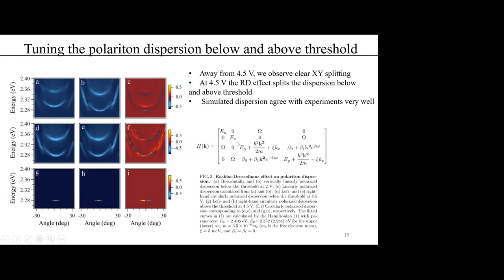In theory, we use this model, which was developed by our collaborators, Mashika and Stefan, in the circular polarization basis. Here, Ex is the exciton energy, and for different spins, they are the same. We assume the two cavity photon modes are near resonant, denoted by EP, and have the same effective mass. The two cavity photon modes are perpendicularly linearly polarized and have different parity. The former leads to them strongly coupling to their corresponding excitons with the coupling strength omega, and the latter leads to the Rashba-Dresselhaus effect with the spin splitting strength epsilon along the Kx direction.